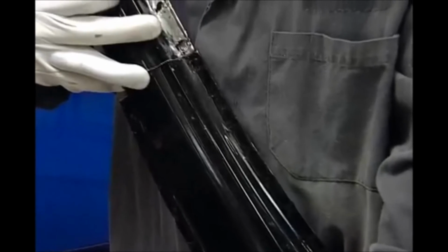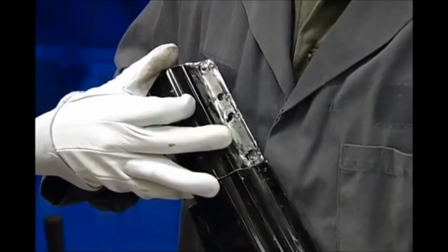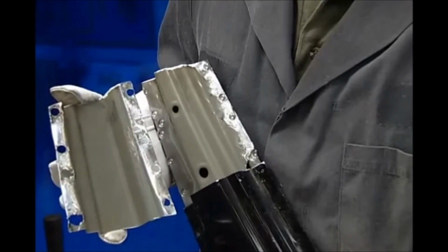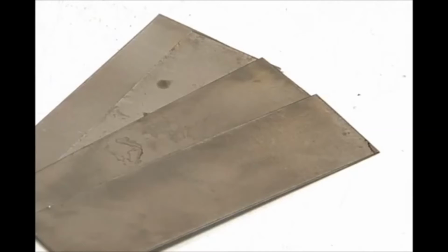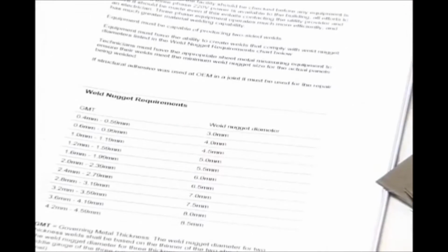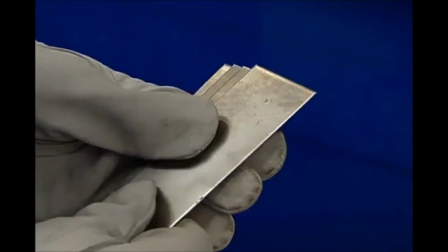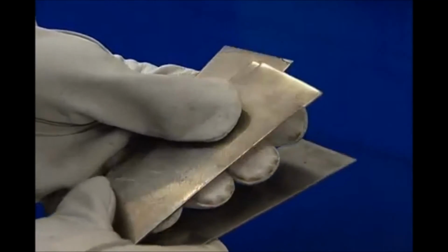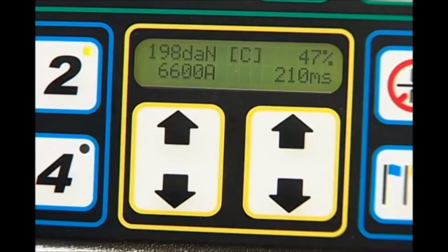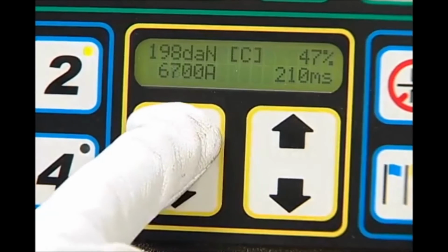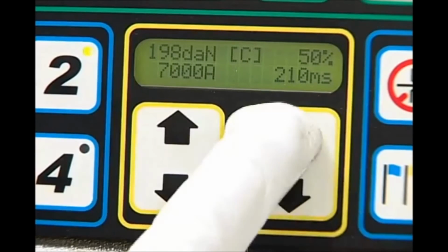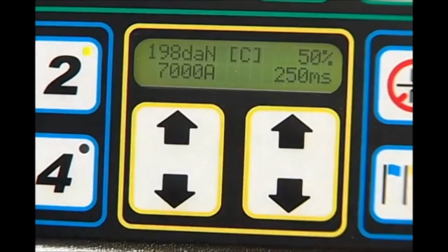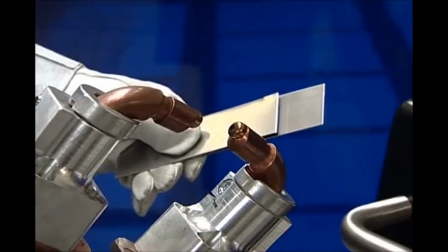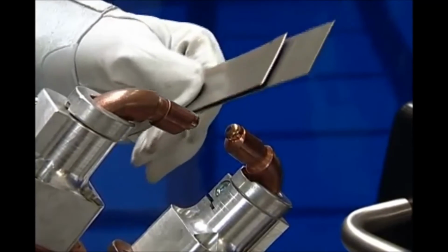For weld quality testing on an actual panel replacement, coupons should be cut from the discarded panel and the vehicle manufacturer's recommendations used for weld nugget size. For the purpose of this demonstration, we're using pre-cut mild steel coupons and the welder manufacturer's recommendations for weld nugget size. Ensure the test coupons are clean and free of all contaminants. The spot welder is set at approximately 200 decanewtons of clamping force, 7,000 amps of current, and 250 milliseconds of weld time. Stack the test plates together with a slight offset and place them between the welder arm tips.